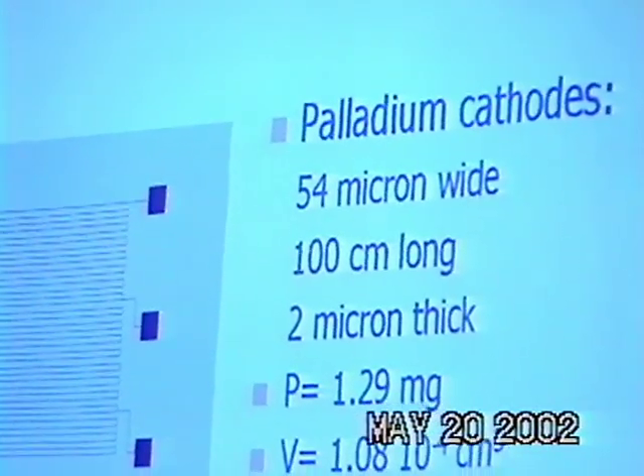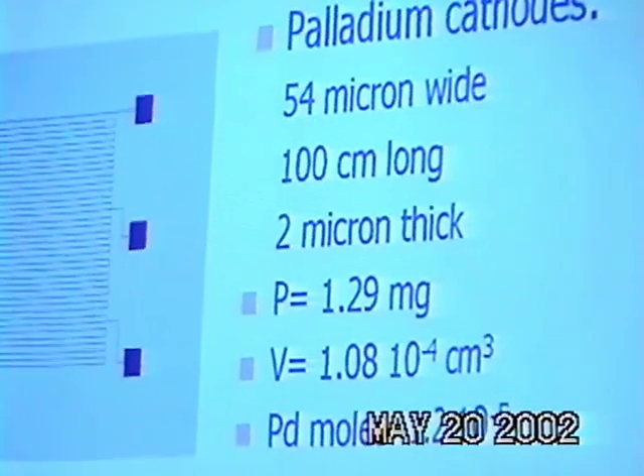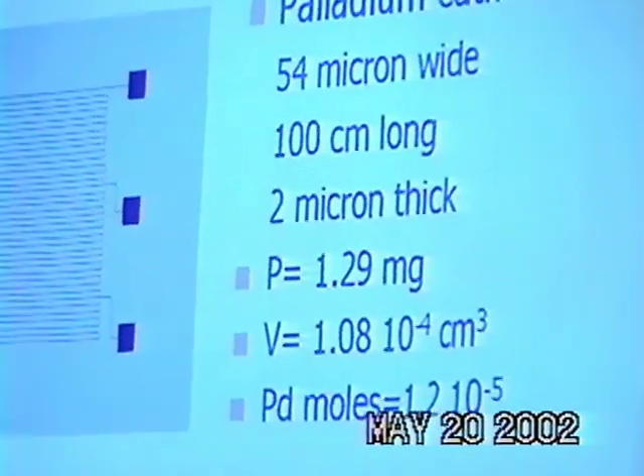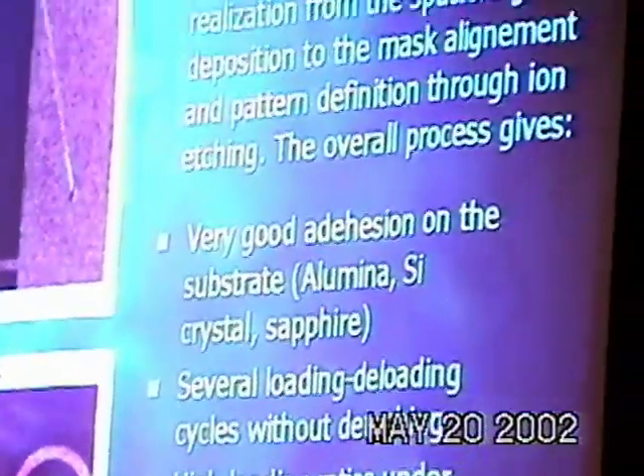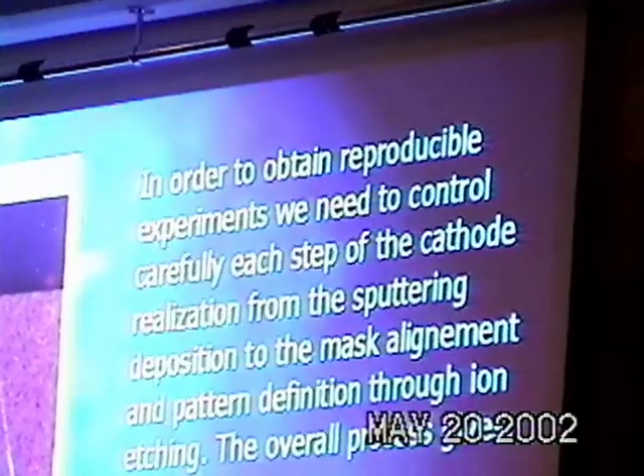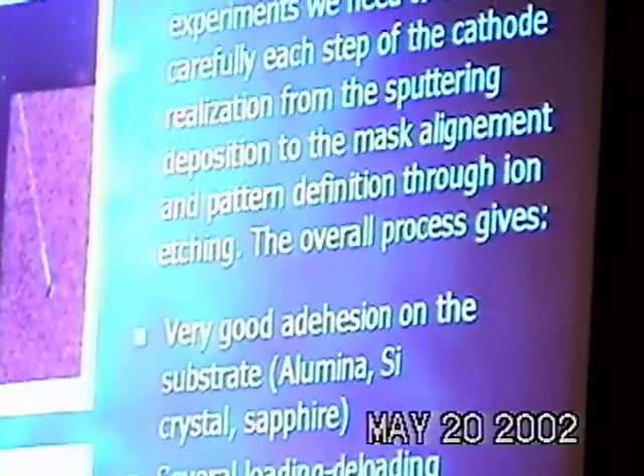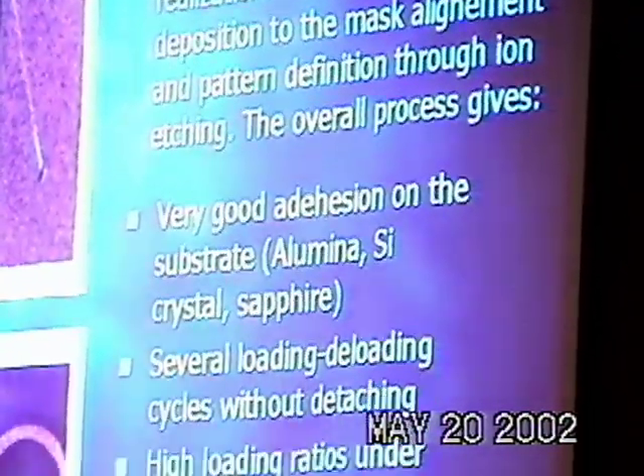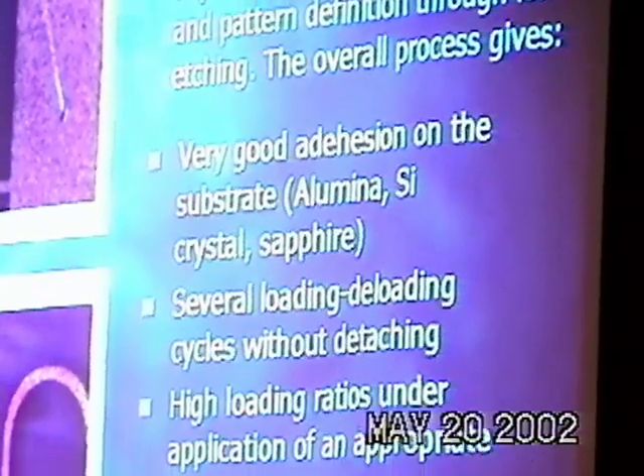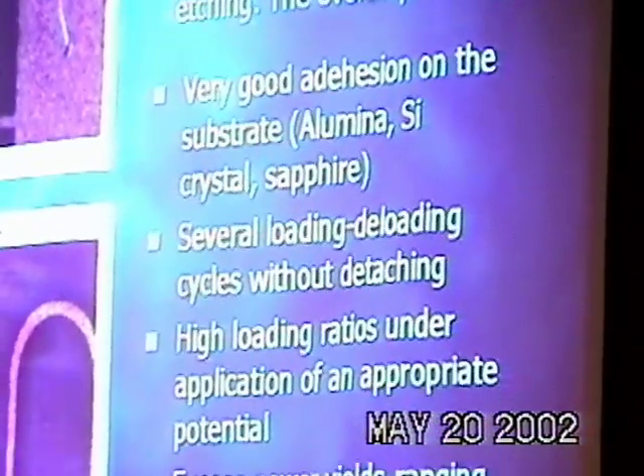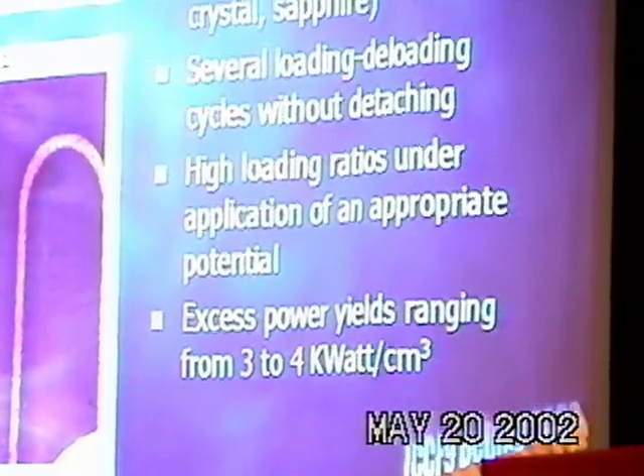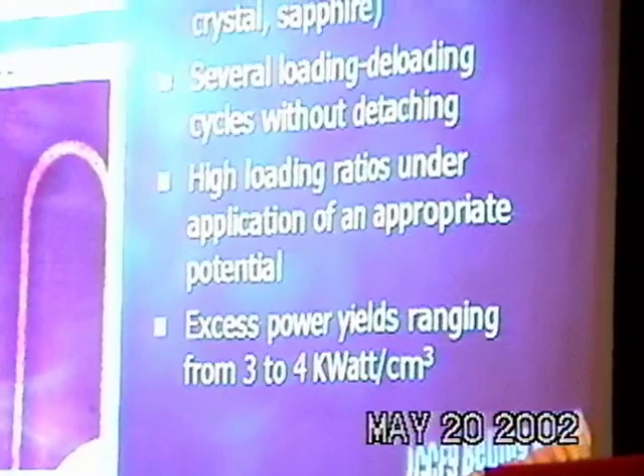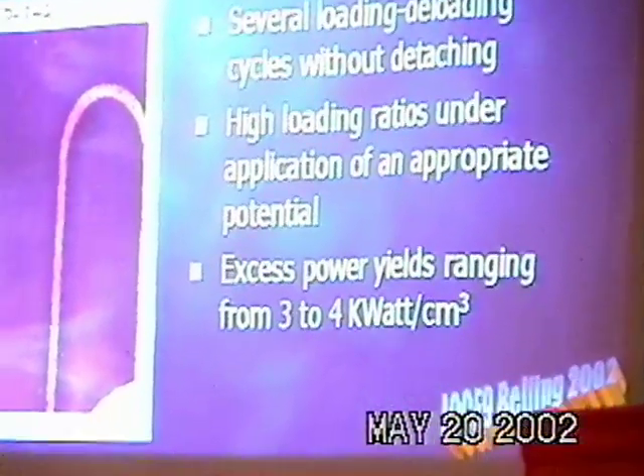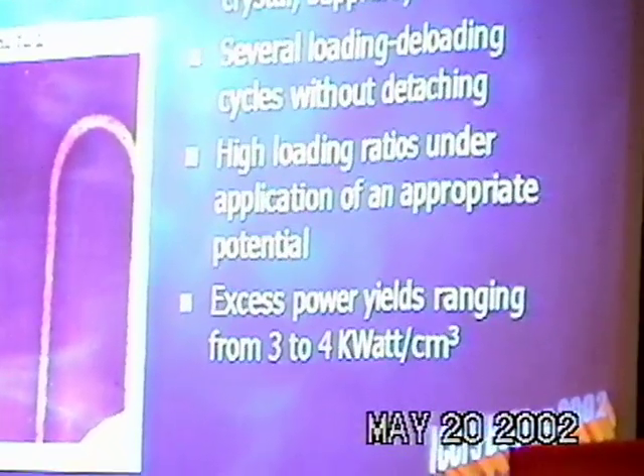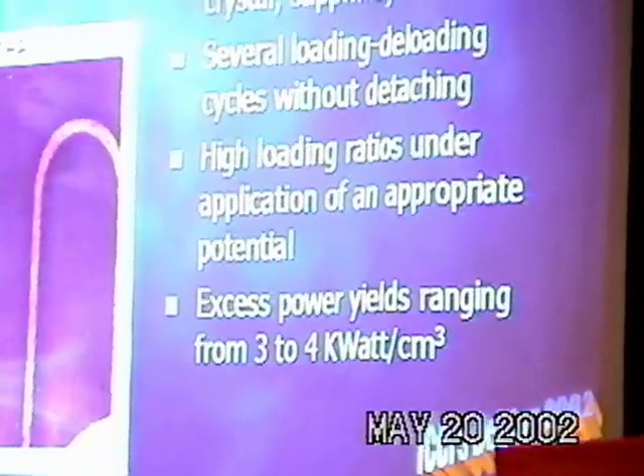To obtain a cathode in such a way is not easy, as many among you know. To obtain a reproducible experiment, it's very important to have a very reproducible cathode that doesn't peel off during the experiment and survives hydrogen loading. You know that when hydrogen enters the palladium lattice, it deforms the lattice up to 10% of its dimension.